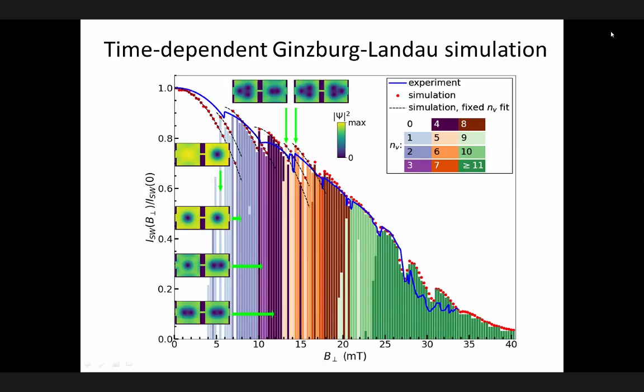And if you look at the simulation, here also with these bars, you see that these configurations are established upon field cooling of the structure. So always, before sending the actual measuring pulse, I first send an annealing pulse. This initialization pulse overheats my structure above TC, above 1.3 K, and now when it is inertially cooled down due to electron-phonon coupling, the thermodynamically stable state is established, and upon exceeding a certain magnetic field, this is the state with vortex.